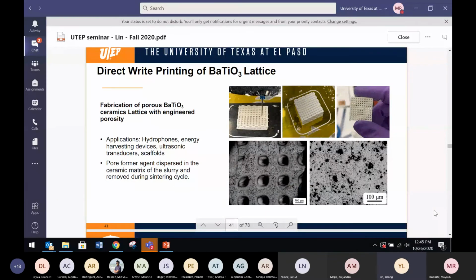All right, so the other thing is we don't want to print just bulk ceramics, right? We want to use the design freedom of 3D printing. So what we're showing here is we can control the processes. Not only can we print the lattice by varying the density from bottom to top, at the same time, we can add polymers, right? During the sintering process, the polymer gets burned away, so therefore you have porosity in it, as you can see in the lower right image. So why do we do that? Because the higher porosity you have, the lower impedance it'll have, or the higher surface area it'll have. So you get better sensitivity, giving you better sensing capabilities, right? So controlling porosity and controlling lattice give you better sensing capabilities.